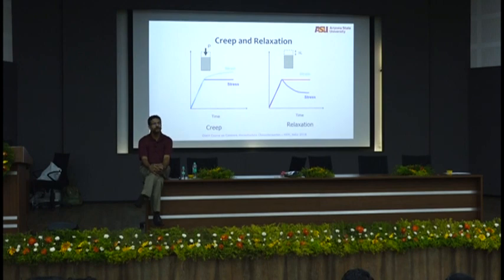Therefore, they drop the strength. Dropping the strength was the best option, so that there is enough relaxation in your concrete to prevent cracking. So creep, relaxation, viscoelasticity are very important ideas when we develop. Again, it goes back to materials by design.